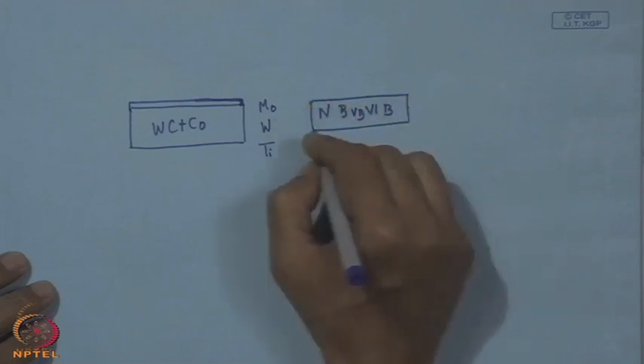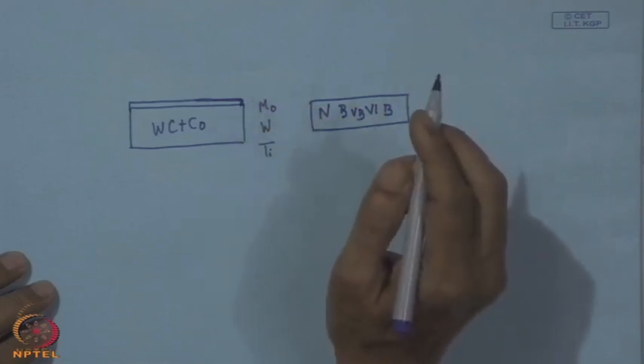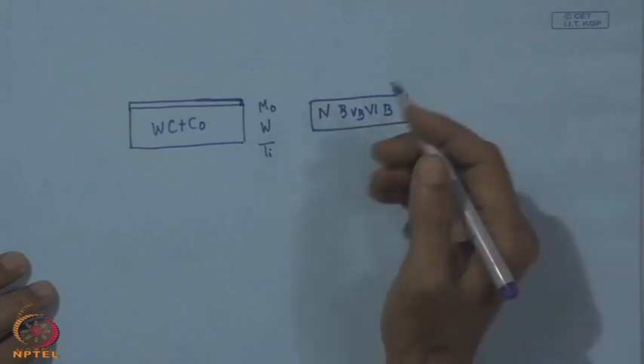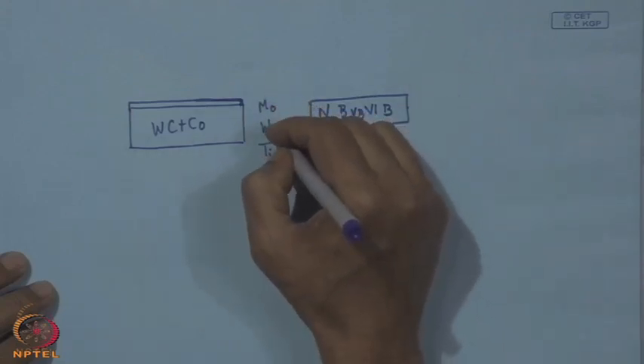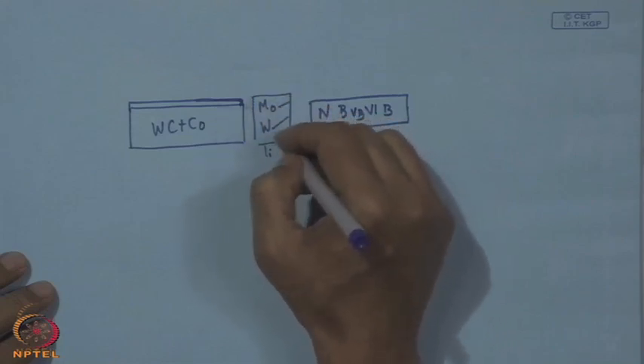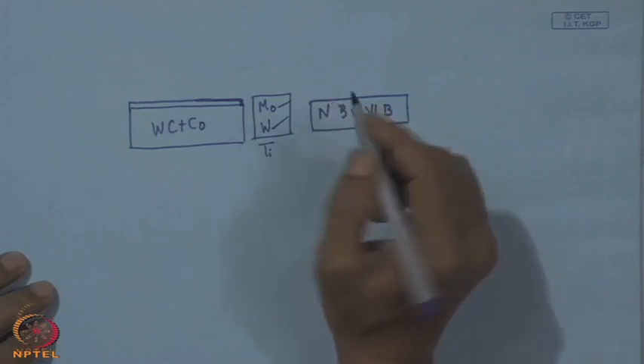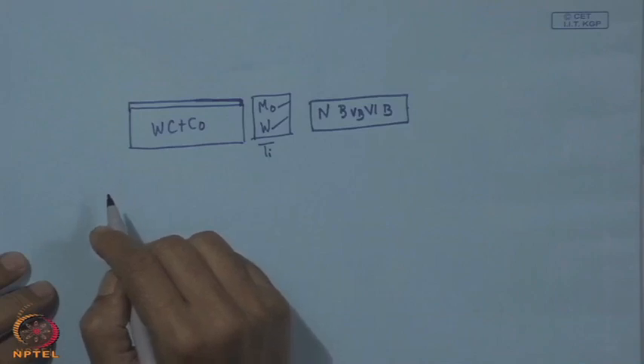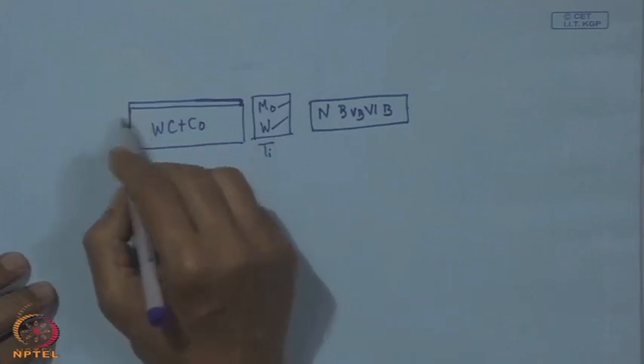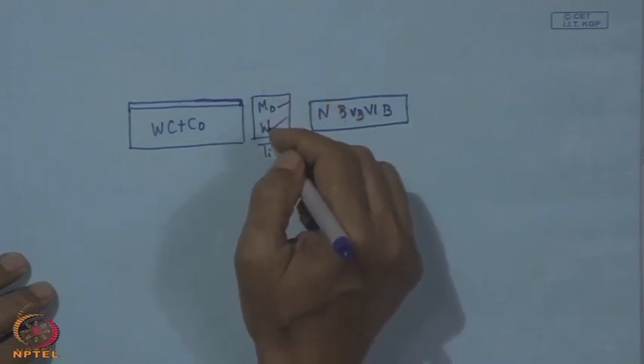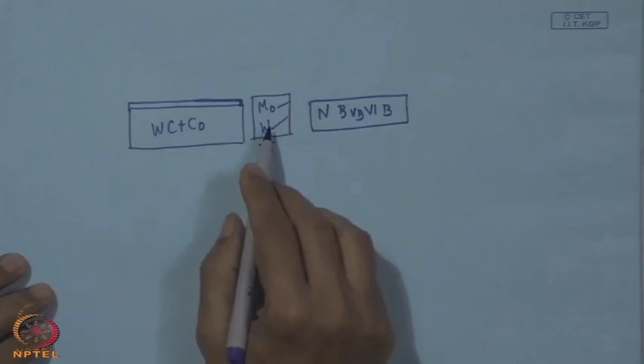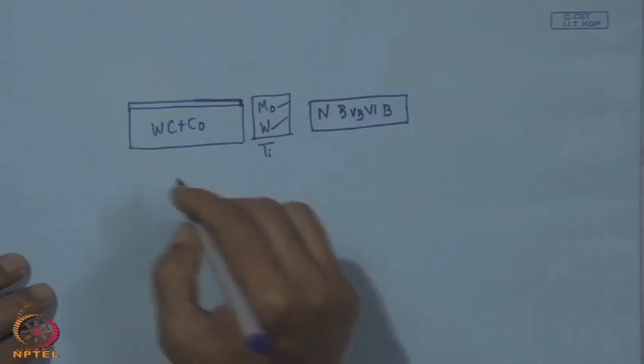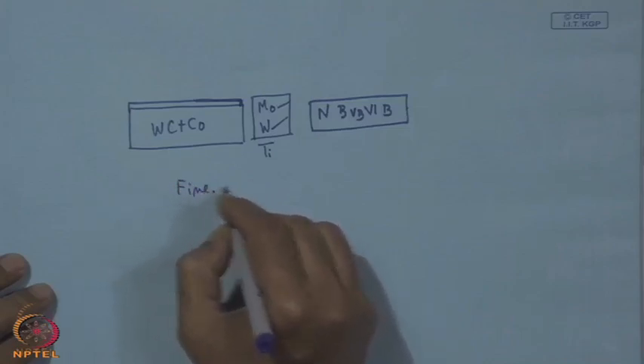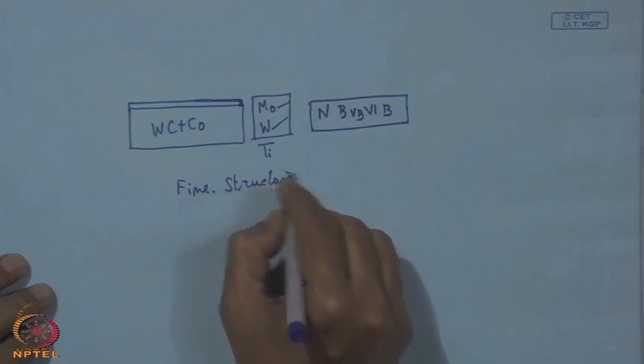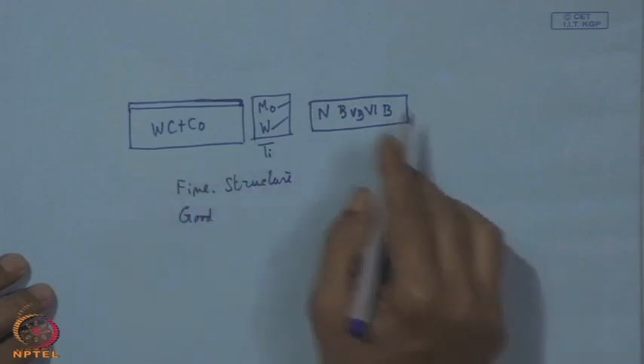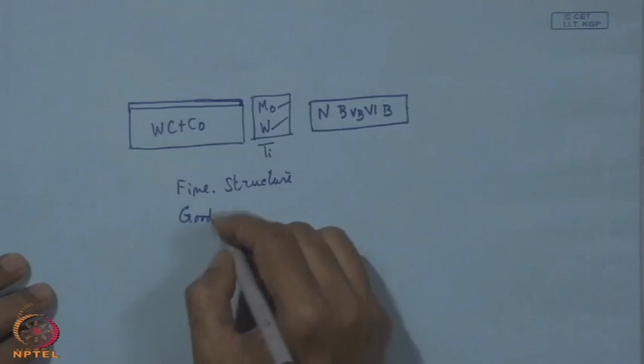These are all transition elements, but not all are compatible. If we look at all those practices done previously, it is mostly molybdenum and tungsten. They are found to be very, very effective in not only suppressing the cobalt layer, but also enhancing the nucleation density of diamond during the CVD deposition process. Because one of the important requirements is a fine grain structure of diamond. Next is good adhesion, and for that so much care has to be taken in the preparation of the substrate.